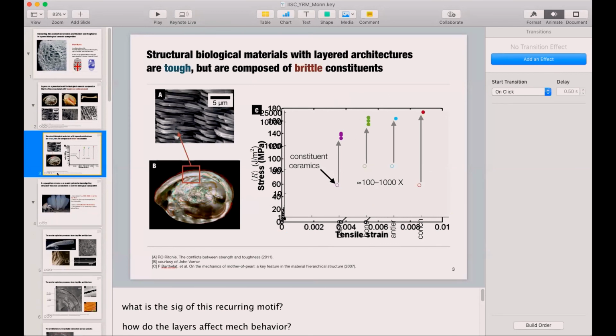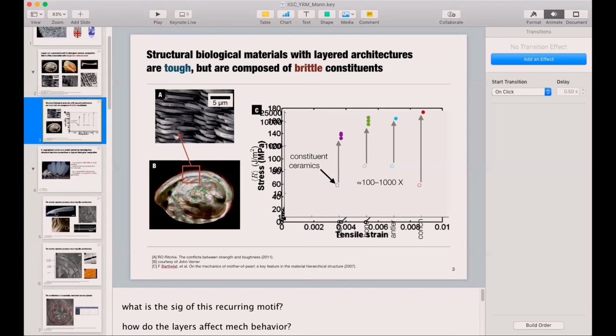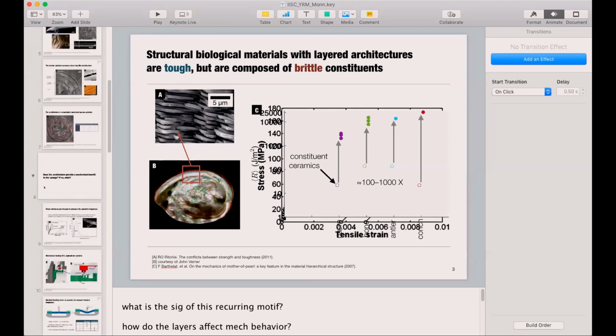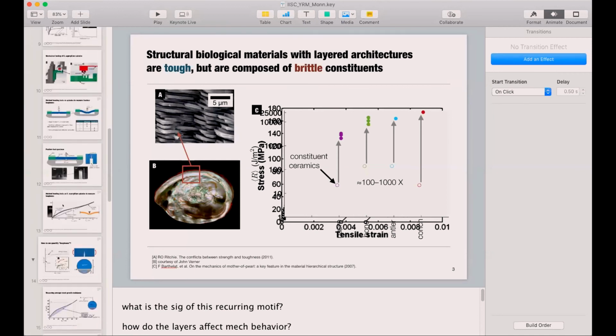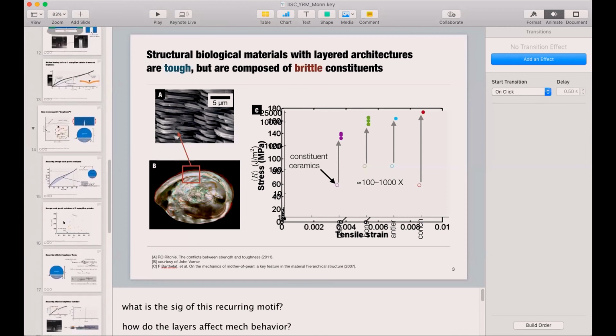There are a very large number of mechanisms that can precipitate these type of enhancements. And so we were mostly focusing in this work on just one, being that Cook-Gordon effect, or nucleation of cracks at weak interfaces ahead of the primary crack tip. And the next question about higher toughness for short cracks. Yeah, the higher toughness for short cracks, that's something that we're still honestly looking into.